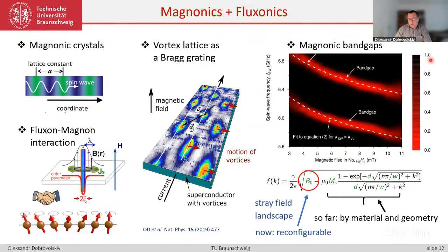And on the right-hand side here, this is just an exemplary plot of spin wave transmission spectra with indicated band gaps, first and second order, because of Bragg scattering of spin waves on the rows of Abrikosov vortices. And these band gaps evolve as a function of magnetic field approximately as 1 over square root of B, where 1 over square root of B is just the Abrikosov relation for the vortex lattice parameter as it scales with increasing magnetic field. But in addition to that, not only the field, we also have the degree of freedom